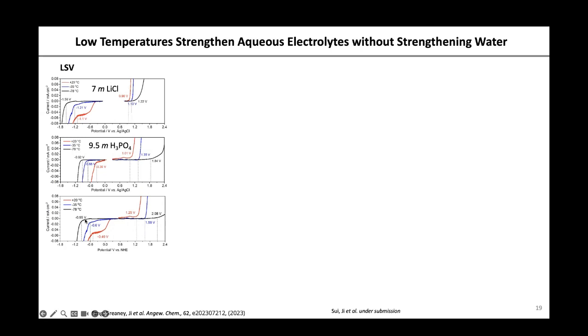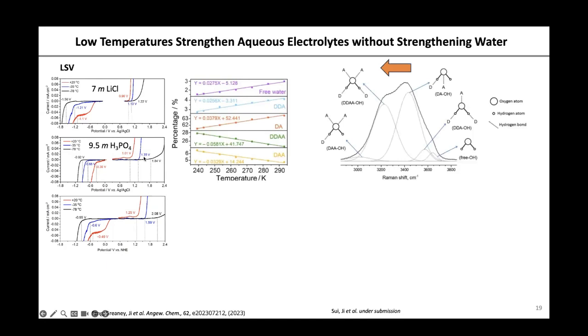Now, the voltage window for water here is not 1.23, it's actually over 3 volts. Why is that? We started Raman again. And we noticed that after lowering the temperature, this section, the lower frequency section, is promoted. We know the lower frequency corresponds to a weak bond enthalpy. So we lower the temperature for the whole solution. Water is less stable because the high strength of the hydrogen bonding is going to weaken the OH bond of water, right? So this is very, very puzzling.